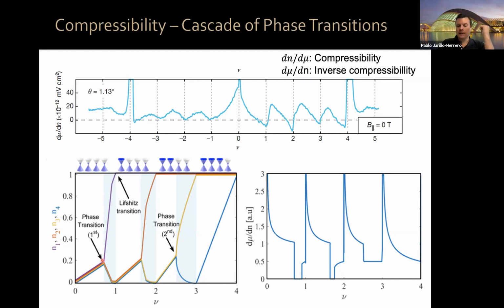However, when I'm close to filling factor 1, so when I'm close to having added 1/4 of an electron to each flavor, 1 electron in total, due to strong interactions, the system decides it's energetically favorable to polarize and send all of the carriers to fill one flavor and empty the other 3 flavors. So the population of one of the flavors goes up and the other 3 flavors go down to 0. And then we start again. We start filling the 3 remaining flavors, initially at the same rate. But then when you're close to filling factor 2, when you have about 1/3 of an electron in each of the 3 remaining flavors, the system again decides to spontaneously flavor polarize due to strong interactions and empty the other 2 flavors, etc. And this repeats itself.